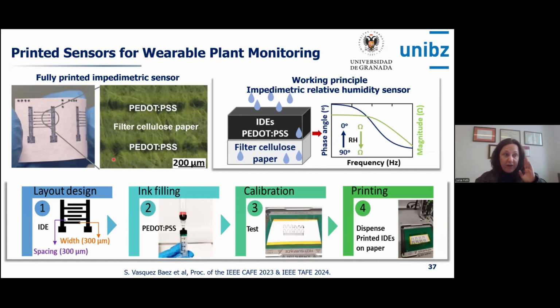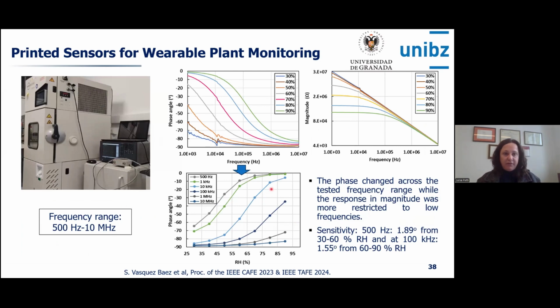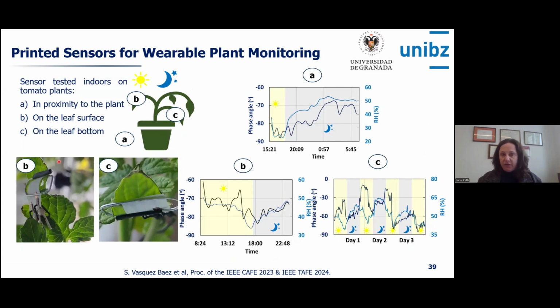But the idea here is to go really on the field, right? Because testing in the lab is easy. I mean, you have impedimetric change with the relative humidity. You characterize your sensor. You make your calibration curves using a climate chamber. But then going in the field is something complex. So what Saira showed is that we can test this on plants, in this case, tomato plants, in various locations, taking benefit of the fact that the sensor is really flexible. It can be attached on the surface, on the leaf, on the bottom of the surface. So you can compare it with the reference sensors that are in the plant environment, but you have additional information by having the sensor directly attached to the interface of the plant.